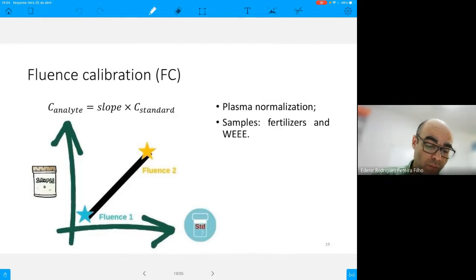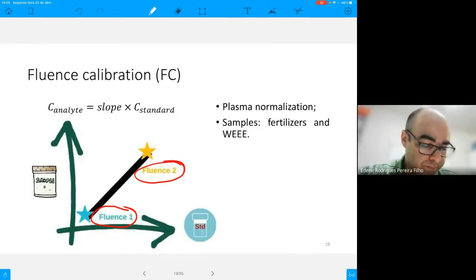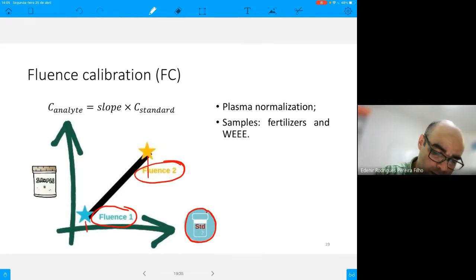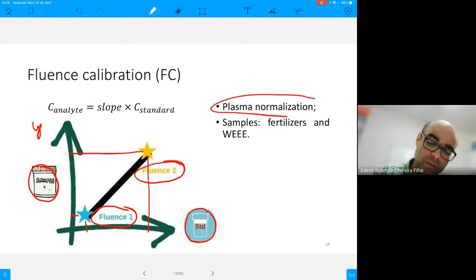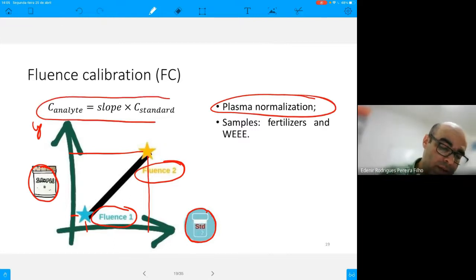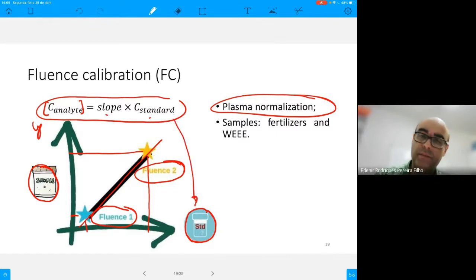Fluence calibration. In fluence calibration, we use two different fluences, Fluence 1 and Fluence 2, in order to normalize the plasma. We have in the x-axis the signal for the standard, the signal obtained in Fluence 1, the signal obtained in Fluence 2, and in the y-axis we have the signal of the analyte for the sample in Fluence 1 and in Fluence 2. We can have also a plasma normalization, and using this equation here, we can calculate the analyte concentration, the slope of this linear model times the concentration of the analyte in the standard. We know this, and then we can calculate the concentration in the sample. We use this strategy in fertilizers and also in electronic waste.